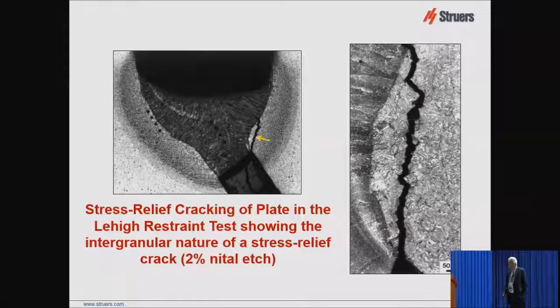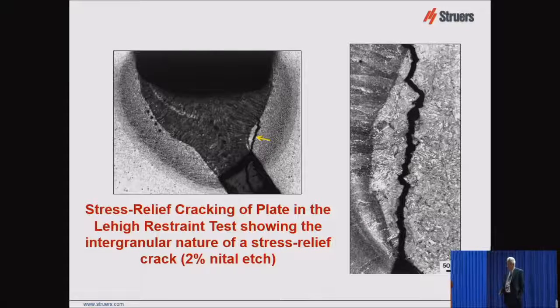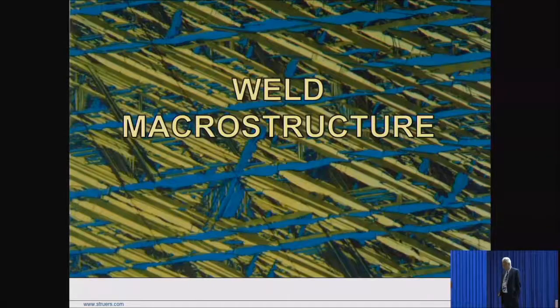You can see these are hardness indents right here, but this is the crack. And over here at 200X, you can see more details of the crack over on this side. And it has a high degree of intergranular fracture. But that's a test that's set up to detect how the stress involved in the weld solidification can cause failures. And obviously this one failed. Let's look at some macro structures next.